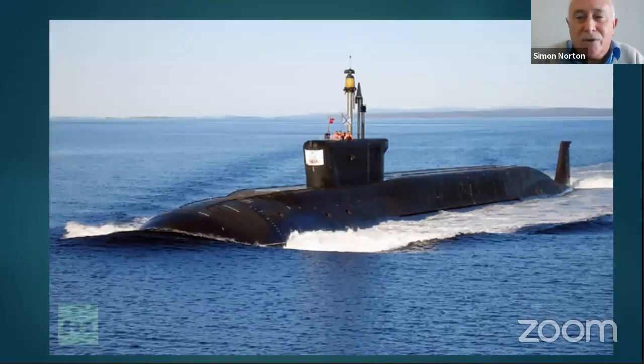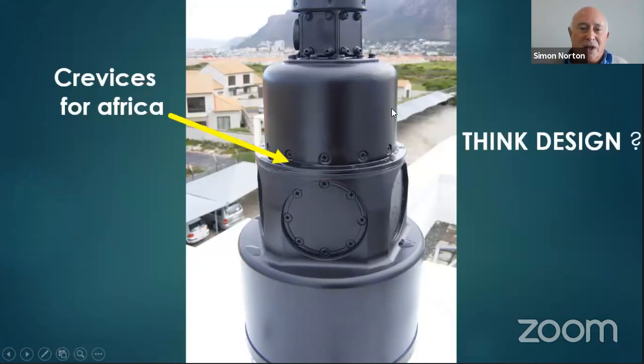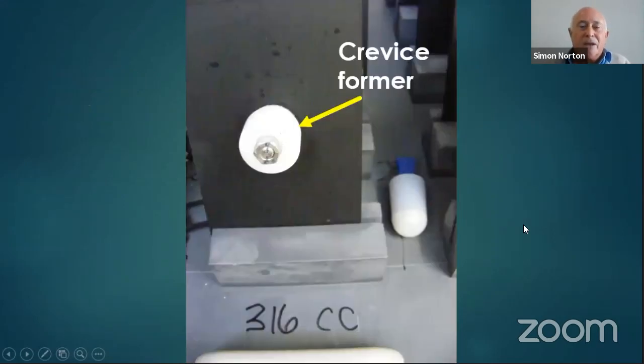Now to some short-term practical discussion. I referred to pitting temperatures, but there are also crevices. This particular machine has very sophisticated equipment on it. And if you look at the top here on the periscope, not only are there optical periscopes, there are electronic periscopes as well. And this is what they could look like. When this was designed, the top part here is made of a composite material, but the rest is made of 316 stainless steel. However, did anybody think about design? Because this device subsequently suffered from crevice corrosion because of the numerous crevices that the machinery required and that couldn't be avoided. So how did we test for that?